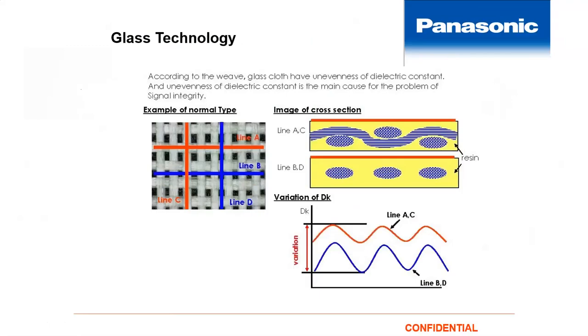And if we've seen these graphs before, the red line with line condition A would be over the top of glass, and line condition B would be where there are gaps, where there's resin, not glass. What that does is change the signal attenuation and the timing, because again the Dk, which determines the speed of the signal, gets lower when you go over pure resin and gets higher when you're going over pure glass.